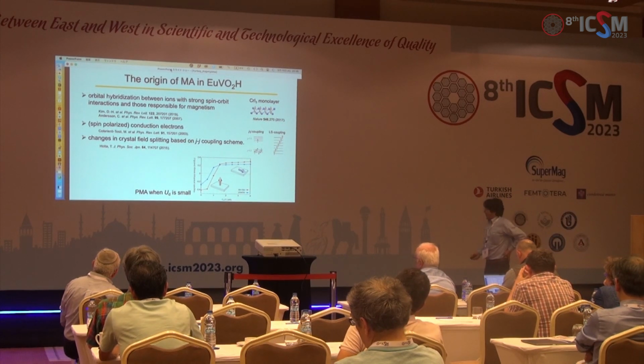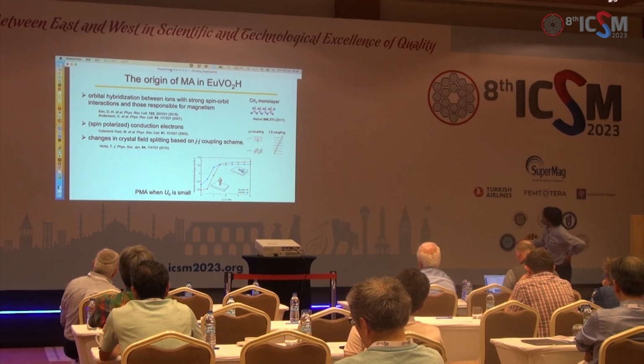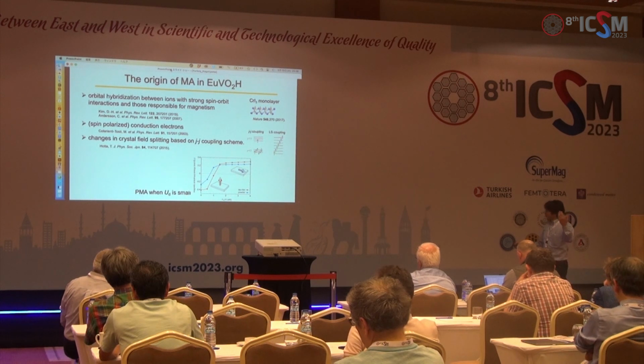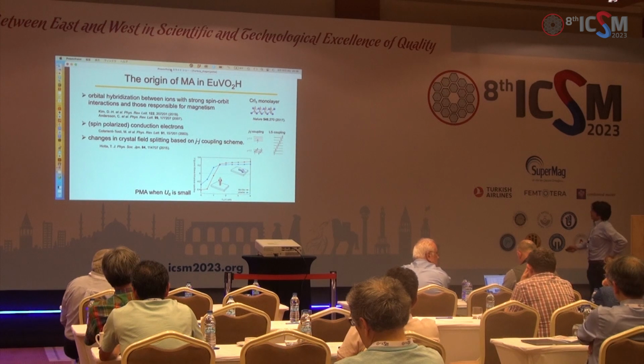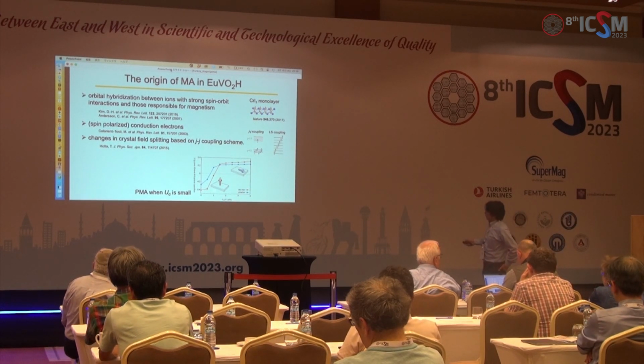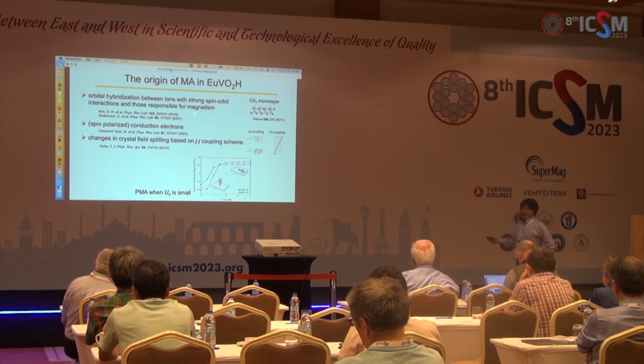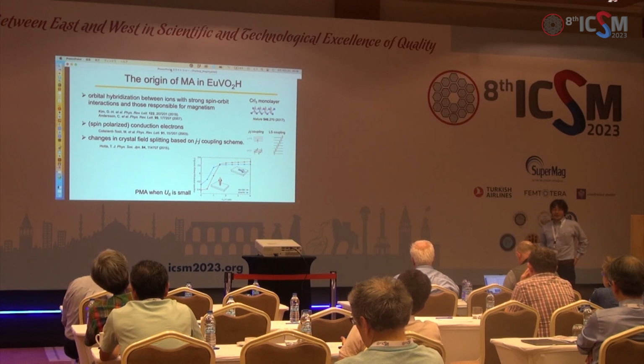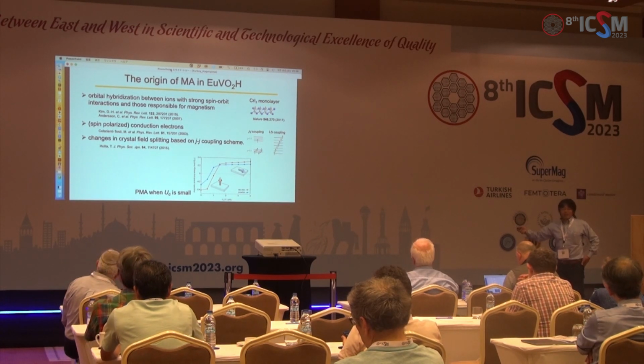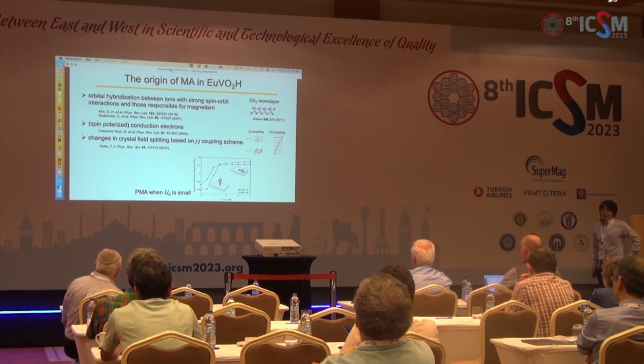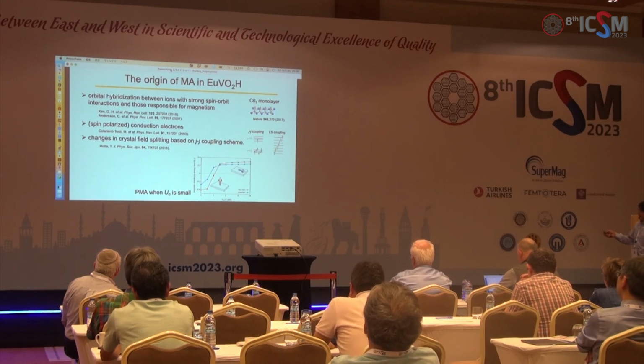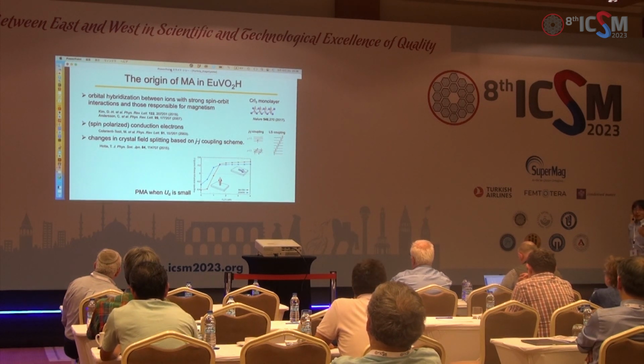So we are not sure, but we asked Dr. Ochi of Osaka University once again, and he calculated the anisotropy, perpendicular or in plane, by changing the U term, the vanadium interactions. Then, as you can see, when this U value is very small, the perpendicular magnetization is realized. But unfortunately, this is not quantitatively agreeing with our observation. In our experiment, we observed that the anisotropy should be as large as 10 Tesla. But unfortunately, this theory gives only much smaller anisotropies. So now we are not so convinced about the origin of the magnetic anisotropy or perpendicular magnetic anisotropy. But maybe this can be found with your help.